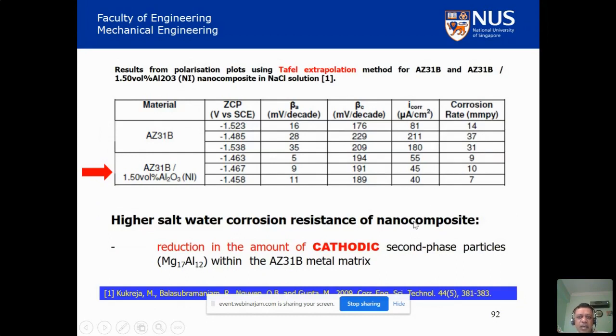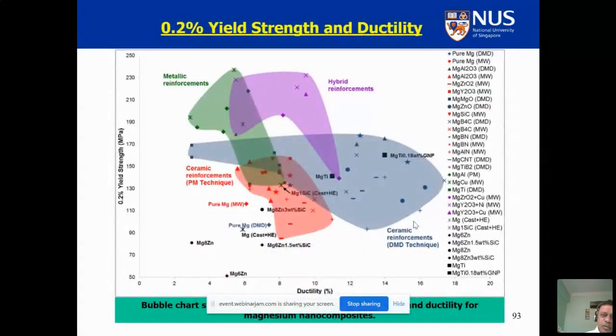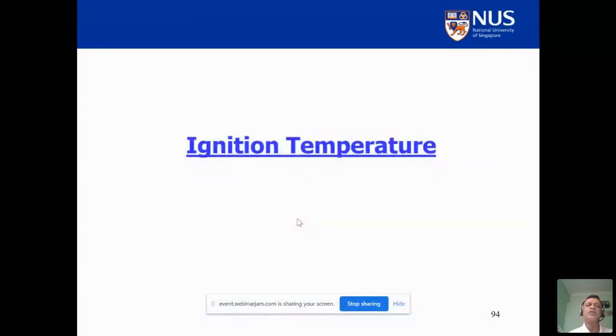And he attributed that to the change in the microstructural condition because of the reduction in the cathodic phases in the microstructure. And to note that if you reduce the cathodic phases in the microstructure, you reduce the wet corrosion. So based on a lot of things, we have developed some bubble charts. And in this bubble chart, you see that the y-axis is 0.2% yield strength, the x-axis is ductility. Then you have hybrid reinforcement, metallic reinforcement, ceramic reinforcement, DMD technique, PM technique. So depending on what strength and ductility combination you want, you can choose the material and you can choose a processing technique.